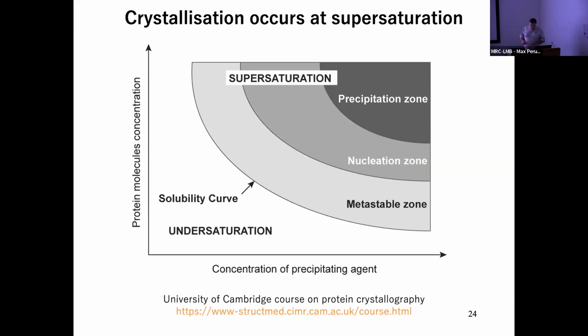This is a bit in contradiction with all the crystallization methods that are based on steadily increasing the saturation. Basically, when you're increasing the saturation, you want to reach the precipitation zone, where you have more chance of nucleation. But then the growth of the crystals occurs in a better way at a lower level of supersaturation, while your experiment is still going higher, triggering more and more saturation. So this limitation is the basis of a method called seeding, that I'm not going to discuss today.